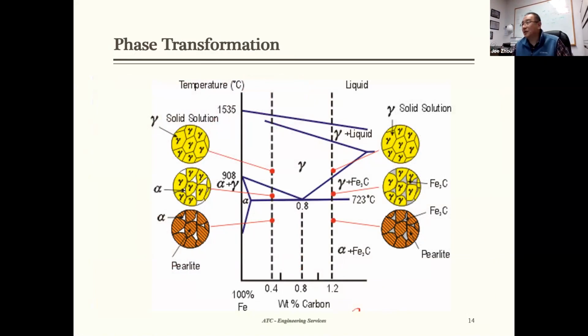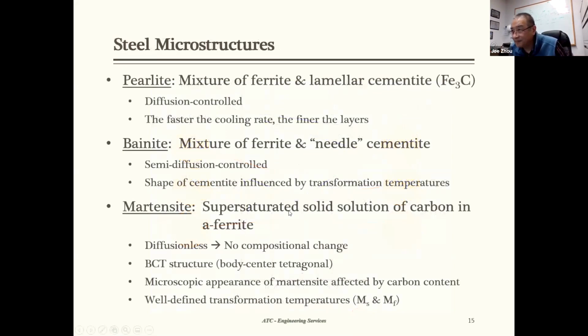This slide is showing you what's going to happen in steel when you're heating up, like a 0.4 carbon. When you pass A1 during the heating, you begin to generate austenite. When you pass A3, the entire steel becomes austenite. Vice versa, when you're cooling down from the austenite and pass A3, you begin forming ferrite. Then keep going, and at the same time you're forming another phase called pearlite, or ferrite plus lamellar cementite.